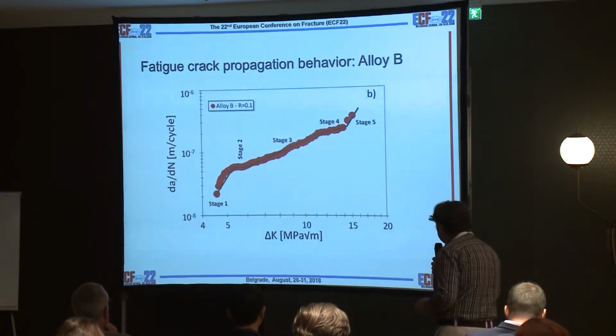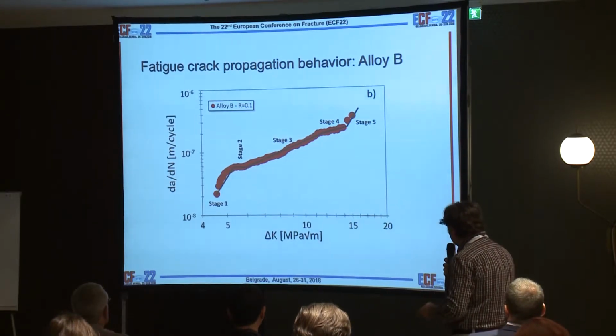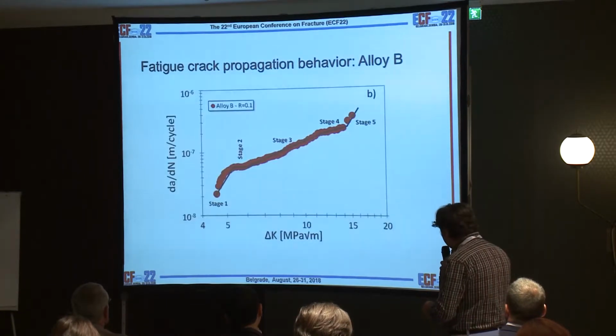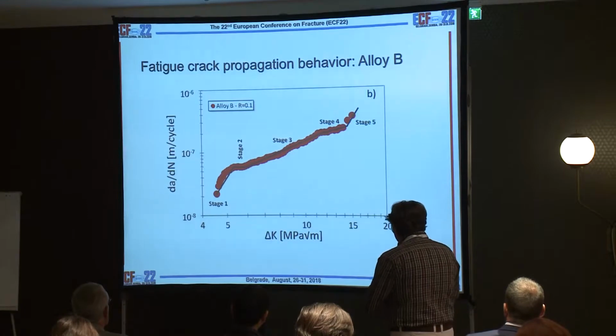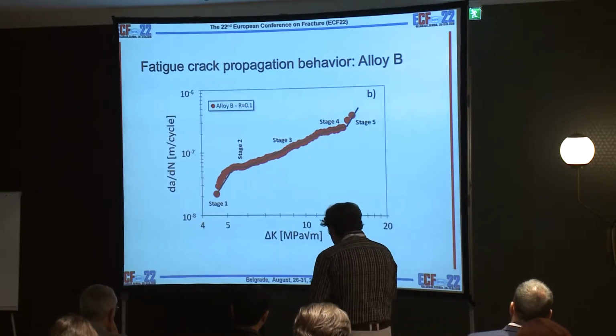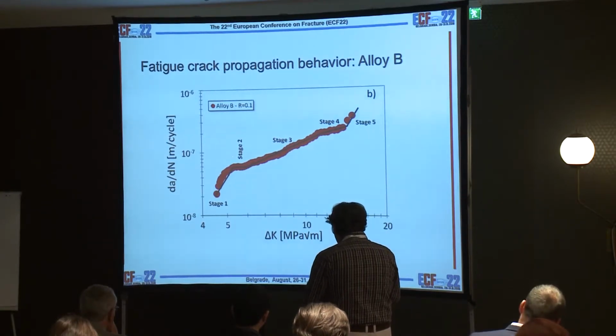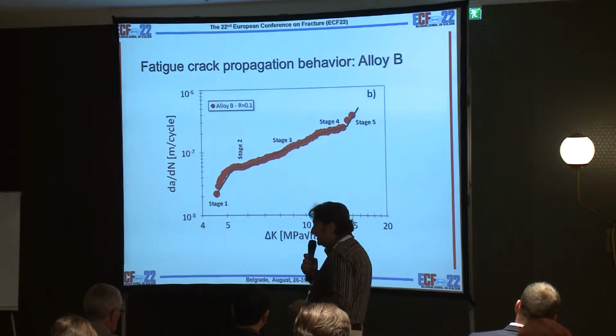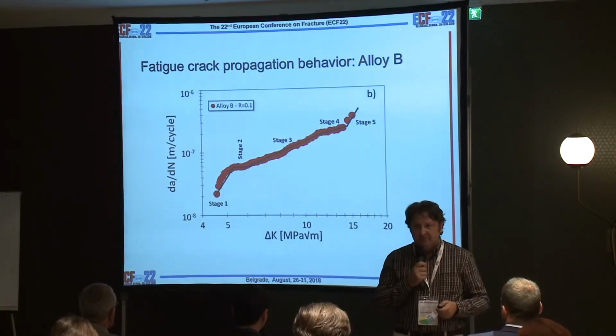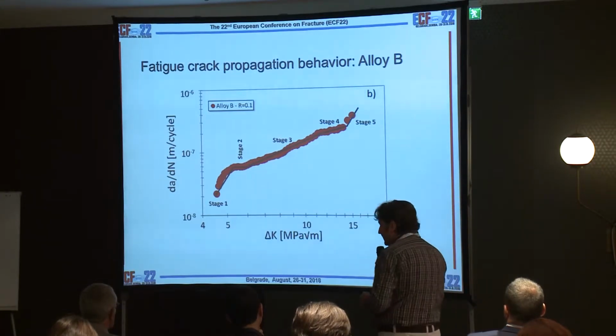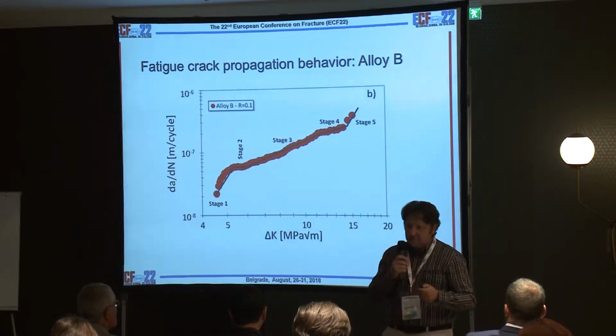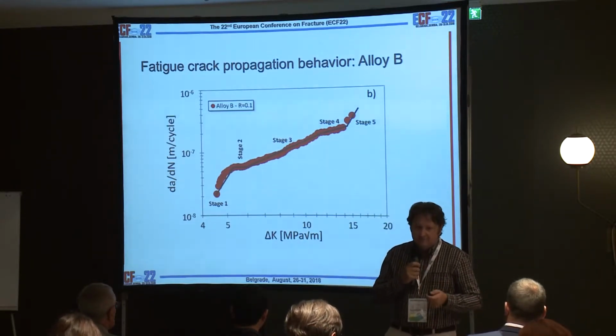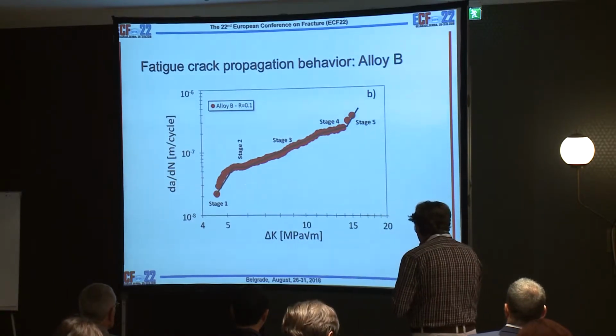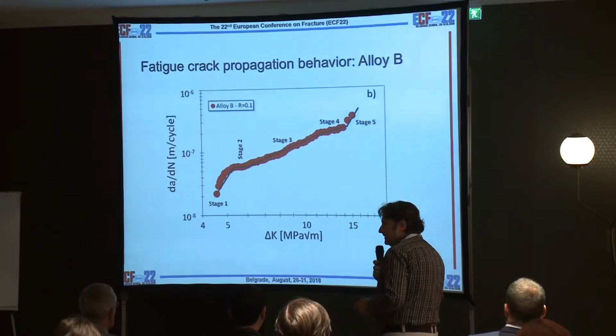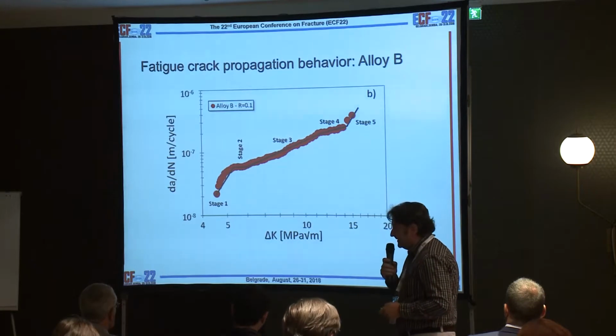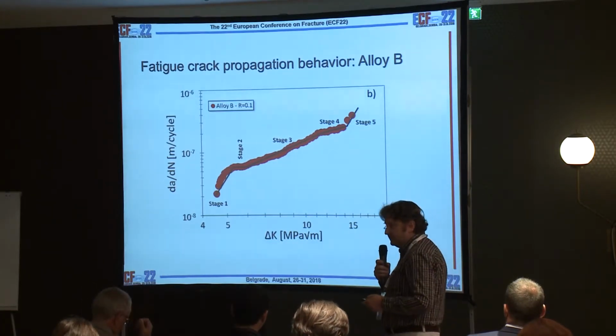The second analysis was performed on alloy B, and it is this. We can see the presence of different stages like alloy A, but the values of delta K of stage 2 are less than alloy A. This is due to the influence of grain size, because the chemical composition seems to be quite similar, and the diffraction spectra of alloy A and alloy B are practically the same. So the width of stage 2 is less than the stage 2 of alloy A.